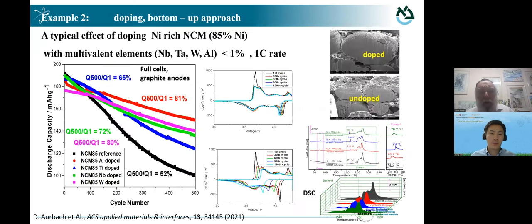Another option, of course, is a bottom-up. We can put sources of dopants like niobium, tantalum, tungsten, aluminum within the precursor. And then the final process is always heating up to more than 700 degrees C. And then we have a distribution of dopants and also segregation, the surface is affected more.